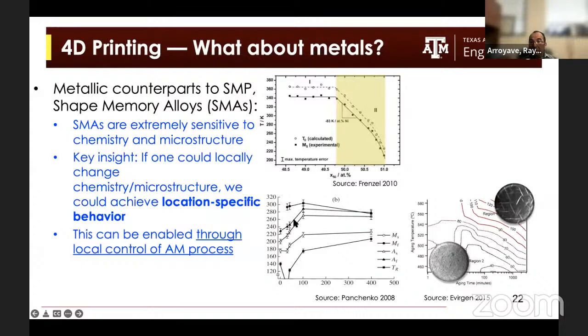More importantly, in addition to this, we have discovered in collaboration with Professor Karaman that if you subject some of these shape memory alloys to heat treatments, you can dramatically change the transformation behavior by controlling the microstructure of the material, right? So these materials are incredibly sensitive to chemistry and microstructure. So a key insight that we had in our group about, I don't know, 4 years ago was that if we could locally change the chemistry and or microstructure of these materials, we could achieve location-specific behavior. And this could be enabled through the local control of the additive manufacturing process conditions.